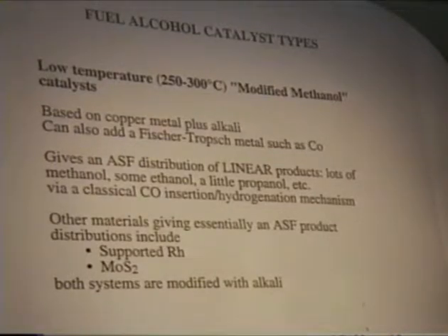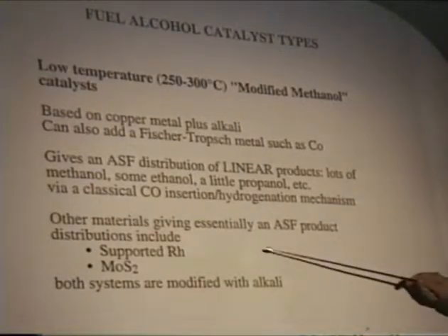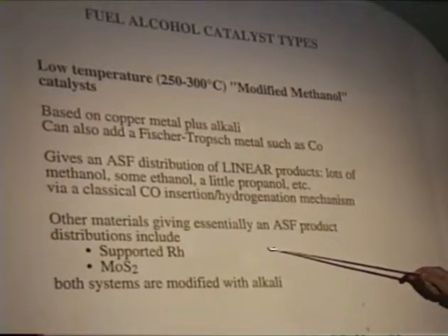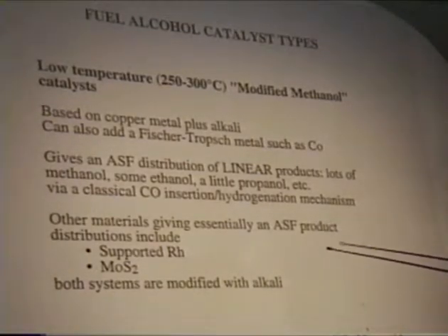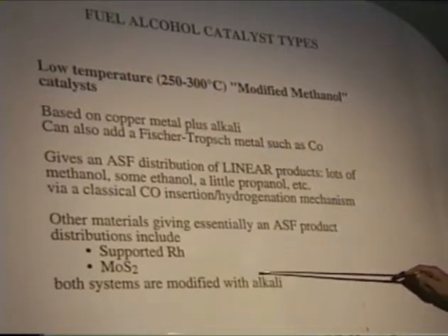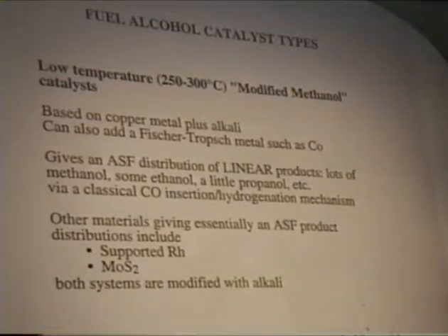There are other materials that give an essentially Anderson-Schulz-Flory product distribution of linear products. Supported rhodium on silica. If this catalyst is optimized correctly, it can actually give you a lot more ethanol than you would expect from the regular Schulz-Flory distribution. And Union Carbide has patents on this, and also on the molysulfide material. All of these systems are modified with alkali.